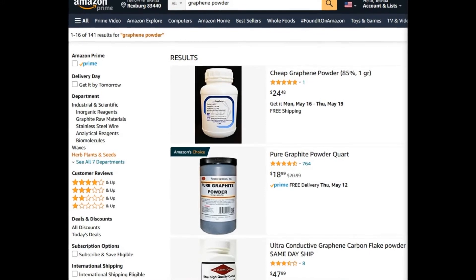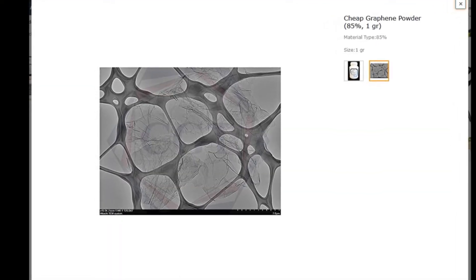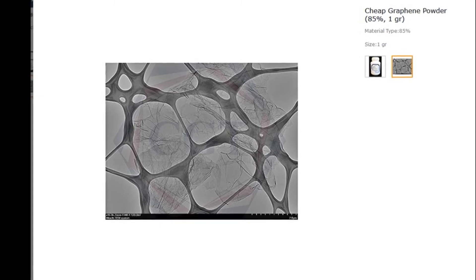There are probably a few explanations. Number one — if you look for graphene powder on Amazon, you'll see many vendors that sell it, and microscopic pictures show it has a flaky, plate-like structure. So even though it looks like a powder to the naked eye, microscopically it looks like large, flat saucers. That rigid, shale-type structure is likely causing it to not fit well into the cracks and valleys of the CPU lid and heat sink base — and if it can't fill those gaps, it won't thermally conduct well.